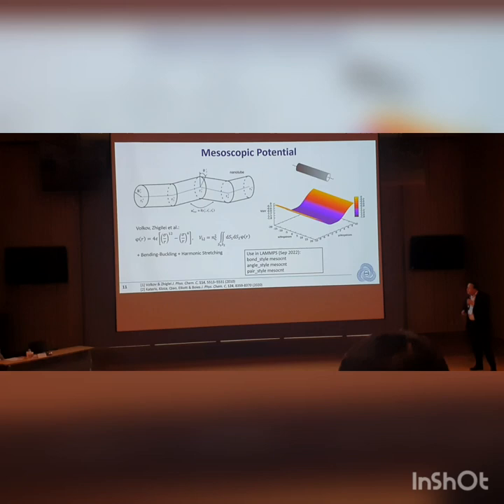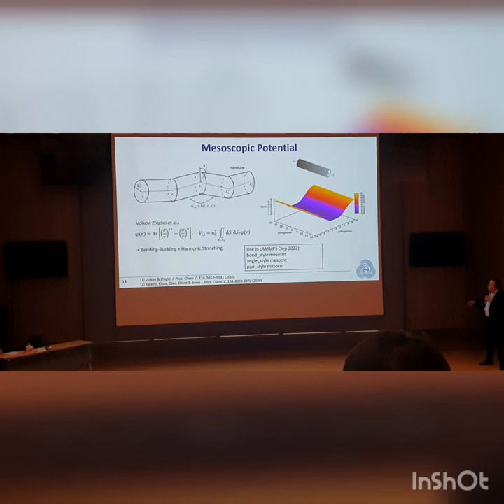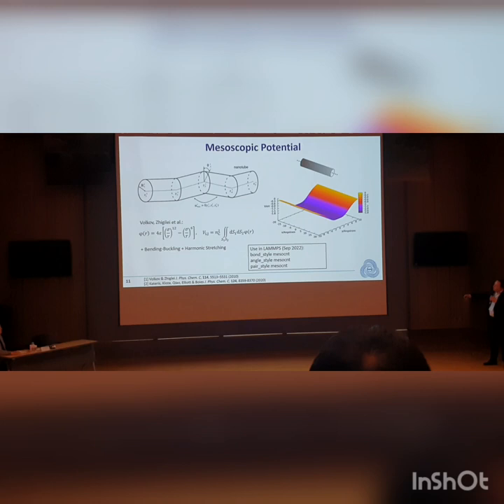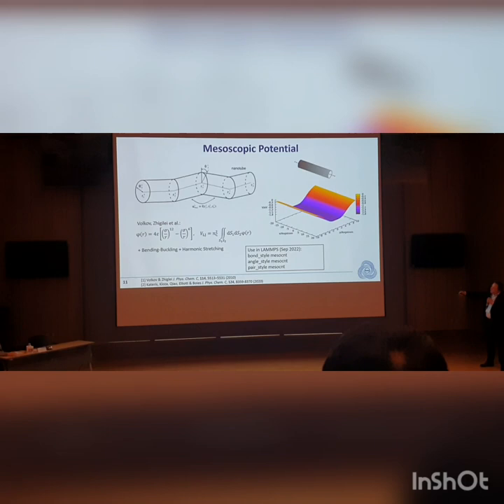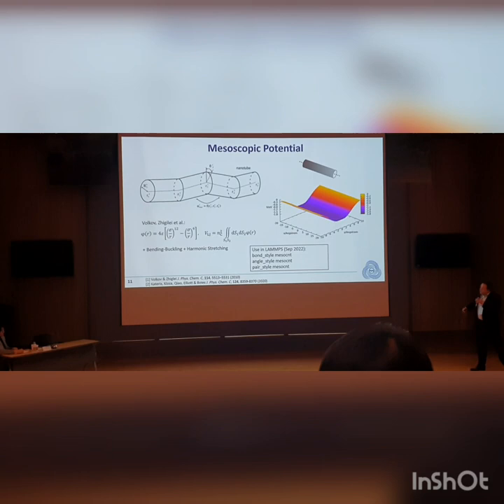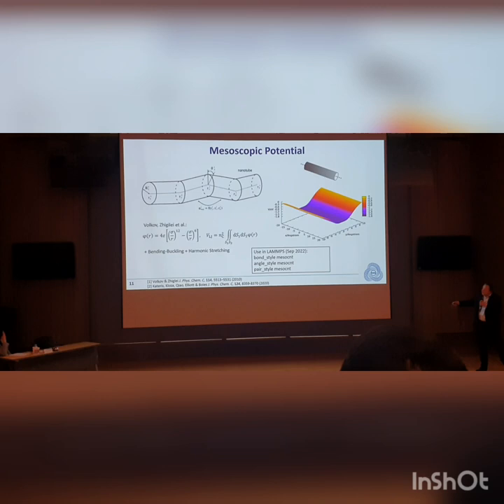To understand this, we want to build models. We start by building a nanotube model we can scale up to look at large-scale fibers. We use a coarse-grained model where segments are connected by harmonic springs with a bending force and a twisting force defined between them. They also interact by van der Waals forces, so they're sticky. Rather than describing van der Waals forces by individual atom–atom interactions, we integrate them along the length of the tube.